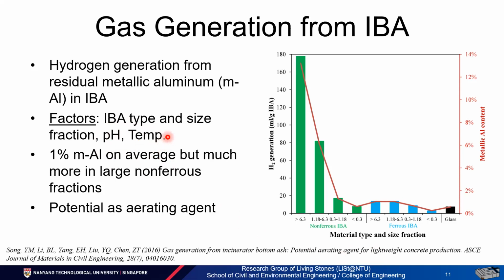When you measure the average gas generation, mixing all size proportions together, it's about 1% - we'd say about 1% of the metallic aluminum content in this average IBA. However, when you measure at different types and size fractions, we find the large non-ferrous particles contain and will generate much more gas.